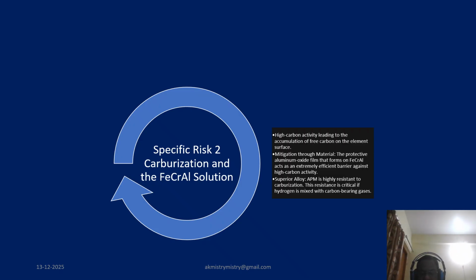Carburization is the risk of high carbon activity leading to accumulation of free carbon on the element surface. Here, the material selection is our mitigation strategy. The protective aluminum oxide film that forms on FeCrAl alloys acts as an extremely efficient barrier against this high carbon activity. Specifically, the superior alloy APM is highly resistant to carburization, a critical factor if our hydrogen is mixed with any carbon bearing gases.